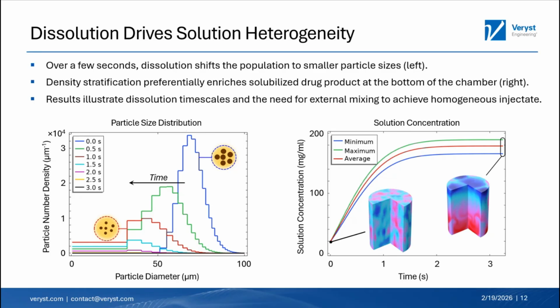And so you can see that in the right plot because there's still a big difference between the min and max solution concentrations spatially. So once the particles have dissolved, there's a vertical concentration gradient, and if you just left this still, it would take potentially days to mix vertically, because this is over about a centimeter. So definitely some active mixing like swishing or some other automated process would be needed to homogenize the solution efficiently.